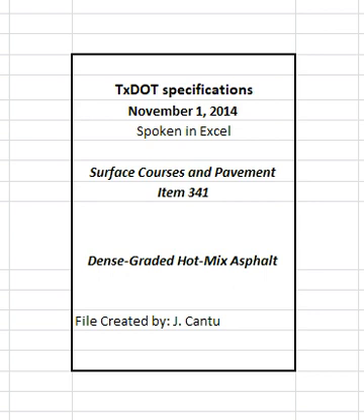The coarse RAP stockpile will contain only material retained by processing over a 3/8 inch or 1/2 inch screen unless otherwise approved. The fine RAP stockpile will contain only material passing the 3/8 inch or 1/2 inch screen unless otherwise approved. The engineer may allow the contractor to use an alternate to the 3/8 inch or 1/2 inch screen to fractionate the RAP.